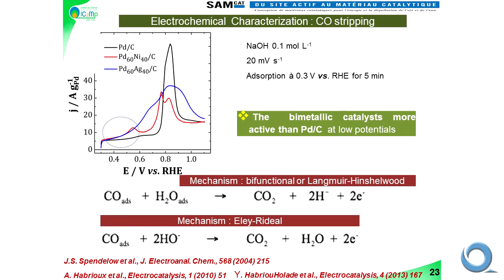And the problem is, how can we oxidize CO without oxygenated species at the surface? This is a big problem in catalysis. Here, we can say that we have a bifunctional Langmuir-Hinshelwood system, because at the surface you have OH, which covers your platinum, palladium catalyst, so you can remove CO by the Langmuir-Hinshelwood mechanism. For example, you combine and you have CO2, and after you diffuse in the solution to become carbonates in an alkaline medium. But at 0.4, there's no oxygen, there are no oxygenated species at the surface. But we have a reaction.